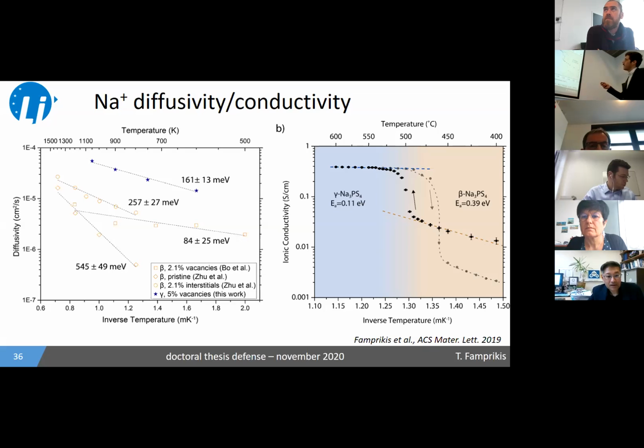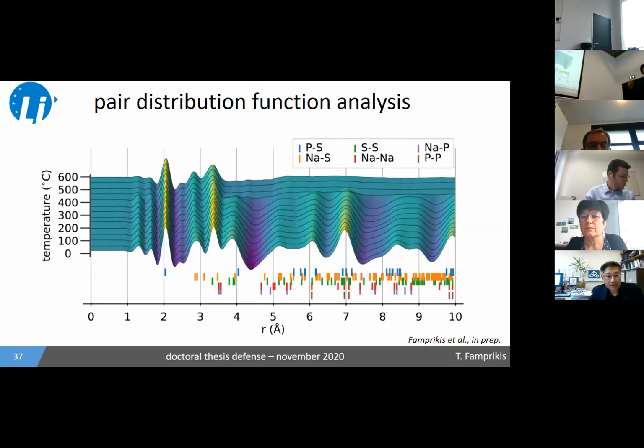I would like to note here the values, right? So this is close to 1 Siemens per centimeter. And the whole effect is reversible upon cooling. So the last data that I would like to show today is the corresponding pair distribution functions as a function of temperature. You can see here. And I would like to quickly highlight what happens upon the beta to gamma transition right about 450, 500 C here.